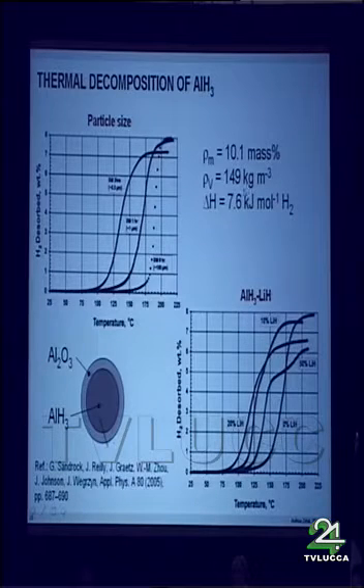Now, when you calculate the decomposition temperature of aluminum hydride based on the heat of decomposition, then it is far below 0 degrees centigrade. So this means aluminum hydride is not really stable at room temperature. It's just kinetically hindered in the decomposition. But it has a very nice property. You can handle it in air, and it doesn't start to decompose, and that is due to the aluminum oxide film surrounding all the grains of aluminum hydride. So now there is again a lot of potential to improve this desorption behavior. Principally, it could work at room temperature already.